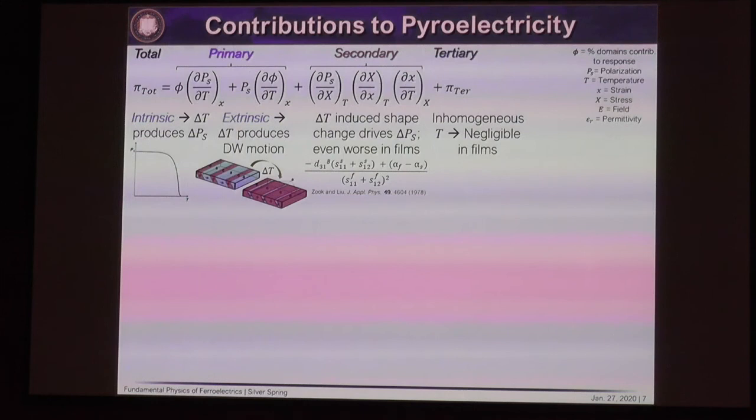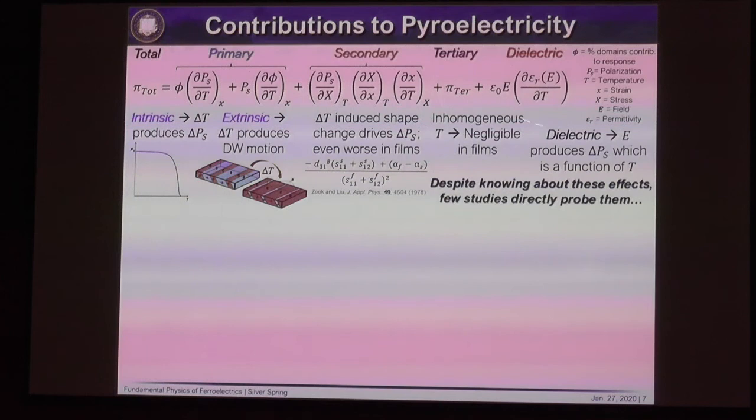And then finally, if you apply an electric field, and some of the applications do require you to change the field while you're doing this, you can have a dielectric contribution to the pyroelectric response. This comes from the fact that this electric field creates a change in the polarization, which also is a function of temperature. And so you can have this dielectric response as well.